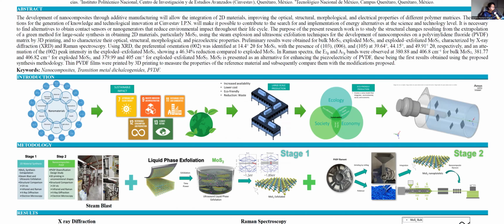As methodology, as we see in our poster, we have a two-step methodology to obtain the exfoliated molybdenum disulfide. First, PVDF was obtained in powder and pellet forms and characterized to assess crystallinity, thermal stability, and morphology. Secondly, for the molybdenum disulfide, we applied a two-step process that separates bulk molybdenum disulfide into different layers. As a goal, we want to obtain monolayers of molybdenum disulfide to work with nanosheets as the precursors of the nanocomposites of PVDF and molybdenum disulfide.